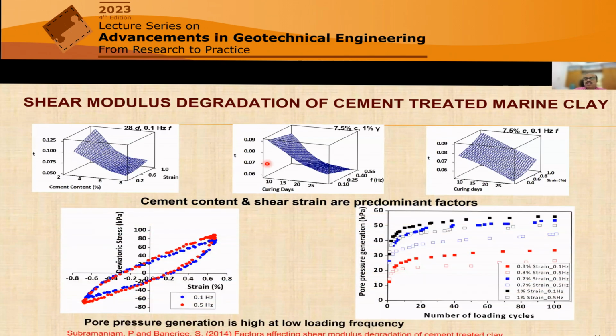We have studied various things. I'm just highlighting here the pore pressure response. If you see the pore pressure generation, these red points are deviatoric stress by strain, and the red points are basically 0.5 hertz, and the blue points are 0.1 hertz, very slow. Now you compare the pore pressure development at 100 cycles, so pore pressure development is there. So you can see, just take any of the strains. Let's take the bottom one.